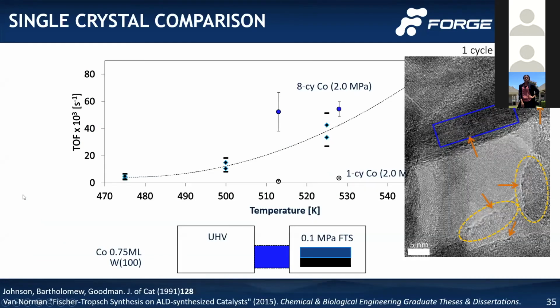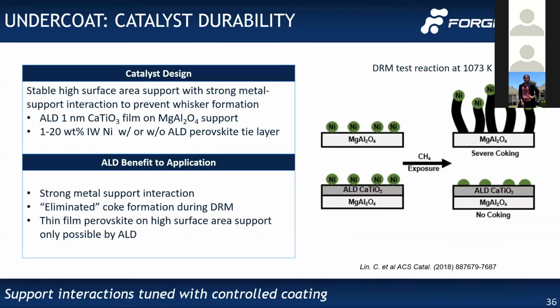Okay, so I'm going to transition now to undercoats and overcoats. When I was at the end of my PhD, I was doing an ARPA-E project where we looked at the commercial viability of the Fischer-Tropsch synthesis reaction. What we determined is that even though we improved the Fischer-Tropsch synthesis, the syngas production was not viable, which made the entire process not viable. So I'm going to highlight where dry reforming of methane can be improved by ALD.